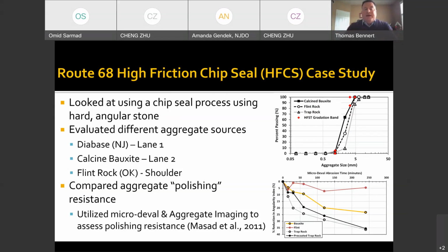There are some different means that we can actually predict the polishing levels in the field in the laboratory using a device called the Micro-Deval, which is a steel cylinder that you put water and small steel shot in with the aggregate, and you abrade those aggregates over time. And then we look at the angularity values in what we call an imaging system, where we're actually taking photographs using computer algorithms to compute the angularity. And on the bottom right, you can see you have different performance of different aggregates. So you can actually pre-screen your materials prior to going out into the field, whether or not your aggregate types are hard enough for these particular applications.